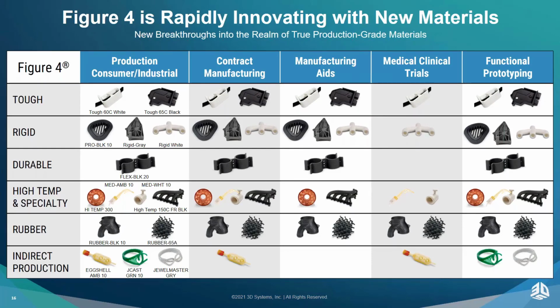Does improving UV stability affect photopolymer curing time? It does not. The UV stability is part of the formulation. So the formulation has many components that drive what that material is going to do. And that's why we say it's engineered in the formulation. There's a real reason that we have not seen long-term stability in additive manufacturing for a long time. And it's one of the nice things at 3D Systems because we have senior material scientists and chemists that can go in and innovate on these different formulations. And in all honesty, Figure 4 is a real breakthrough for additive manufacturing, and what sets it apart from a lot of different products is this long-term stability of these materials. And so as you go in and start looking at the post-cure time, it's going to vary depending on what the full material chemistry is, including viscosity and things like that.